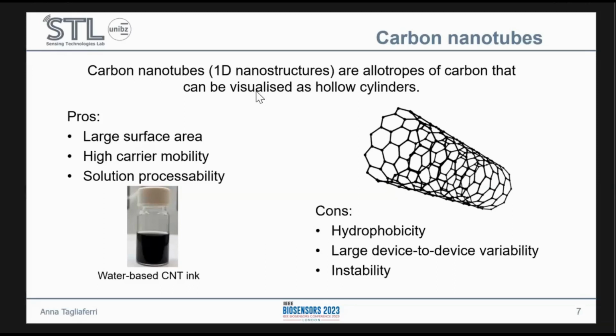On the other hand, they exhibit hydrophobicity. This limits their functionalization in a few instances, and that's why we moved away from the functionalization of carbon nanotubes, preferring the functionalization of the gate electrode. Since we are using a random network of carbon nanotubes, we also see a very large device-to-device variability, which has been somewhat mitigated by the deposition of the membrane. The main thing that we have tried to tackle here is the instability that they show. And by instability, I will show you the results that we obtained without the addition of the membrane.